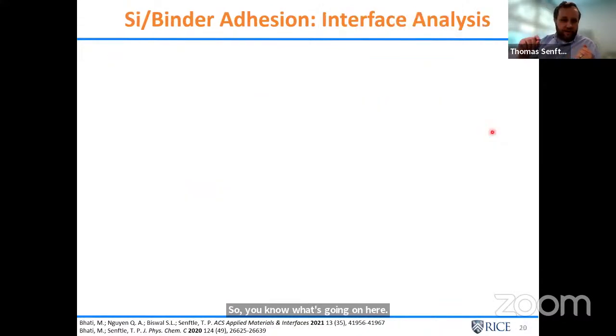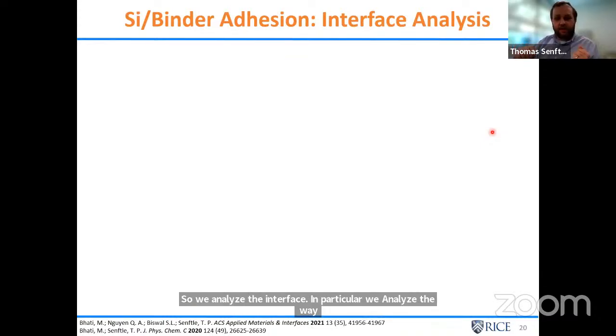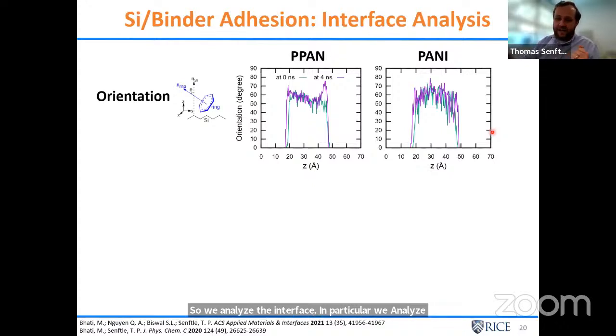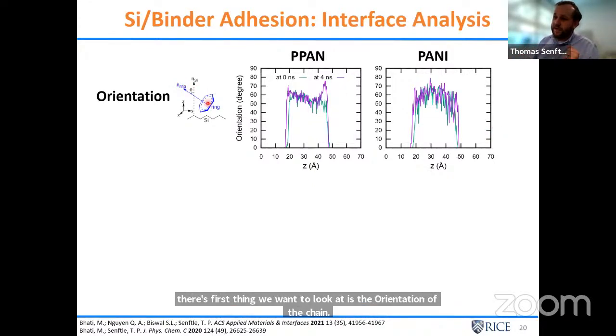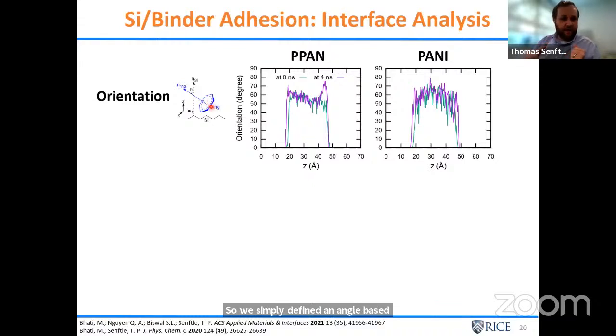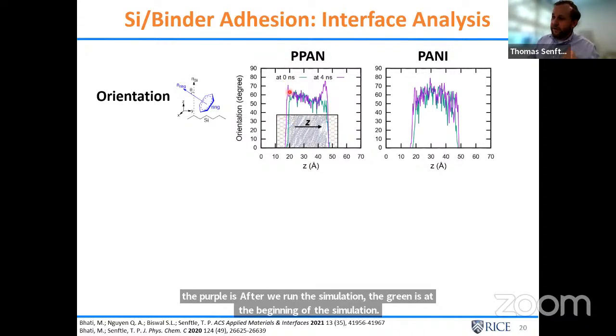So we analyze the interface. In particular, we analyze the way that the polymer is binding on the interface. So the first thing we wanted to look at is the orientation of the chains. So we simply defined an angle based on the normal of the plane of the ring. And if we look at that angle as a function of where the chain is in the system, we see that near the interface, here the purple is after we've run the simulation, the green is at the beginning of the simulation. Right, just to orient you here, we're talking about the interfaces.